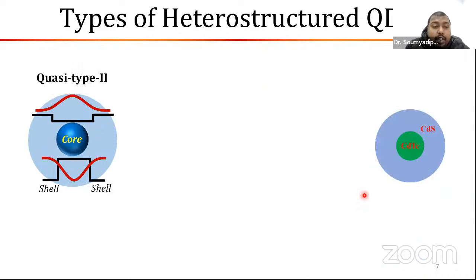And the last of all is quasi-type 2. Quasi-type 2 is basically when you are putting a thick shell over a quantum dot. Here I showed a CdSe/CdS quantum dot. The thing is that here at least one carrier is totally delocalized within the core and the shell system. That means this thick shell can be tuned to make this quasi-type 2 into type 1 or type 2. So you can actually vary from this to the other two structures.